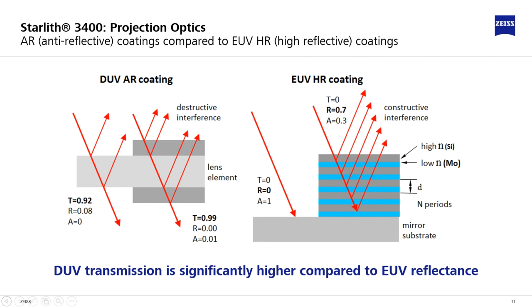For a wavelength of 13.5 nm, multilayers based on molybdenum and silicon have proven to yield the highest peak reflectance. The theoretical maximum for this is 75%, while in practice the reflectance can be higher than 70%. The deep UV transmission is significantly higher compared to the EUV reflectance.